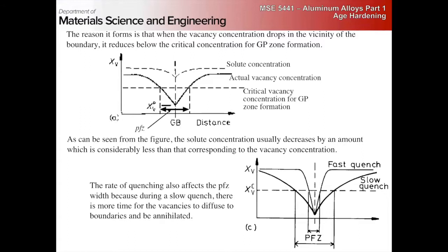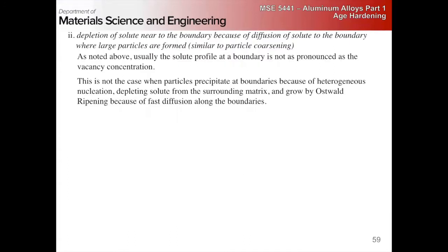Where do we often see secondary phases in polycrystals? Grain boundaries, right? Why do they form at grain boundaries? It's easier to nucleate, but that wouldn't happen unless certain solutes are attracted, segregate preferentially to the grain boundaries. So that's the second reason you can have precipitate-free zones: if you have a solute that segregates to the grain boundary, it will leave a depleted region near that grain boundary so that the secondary phase can't form